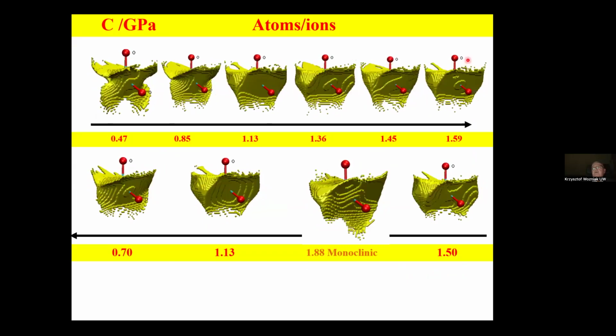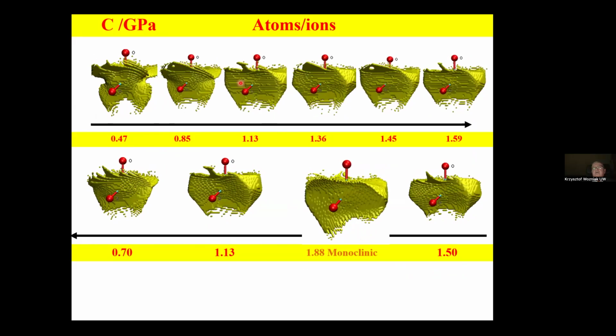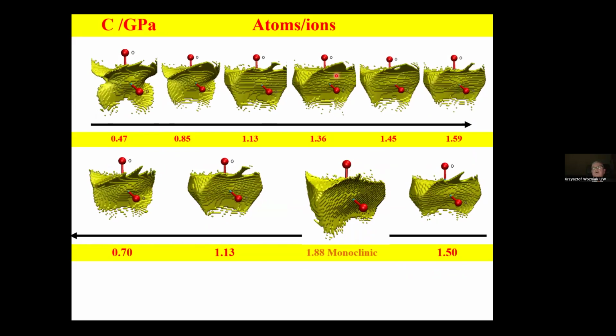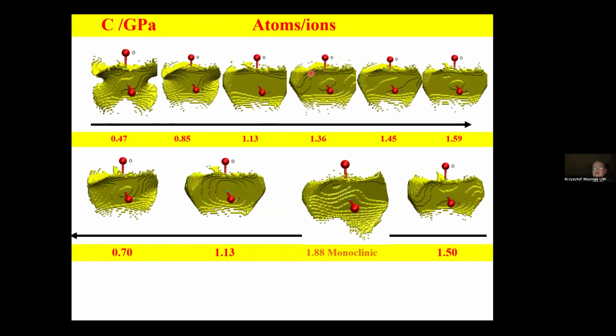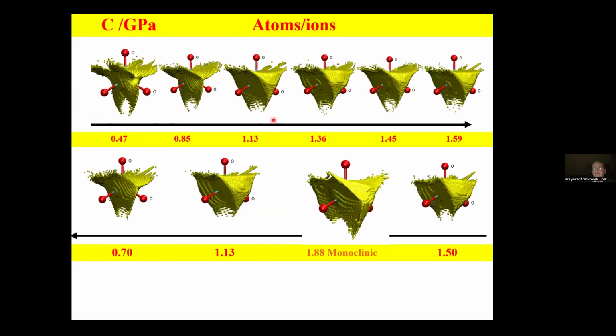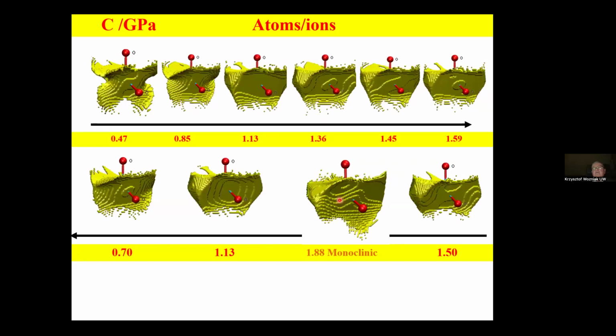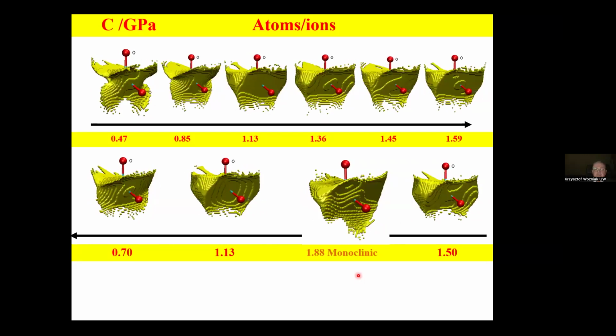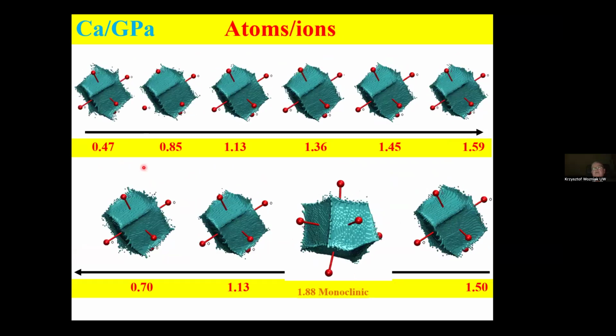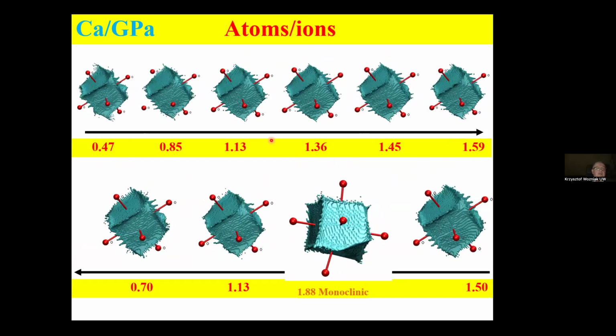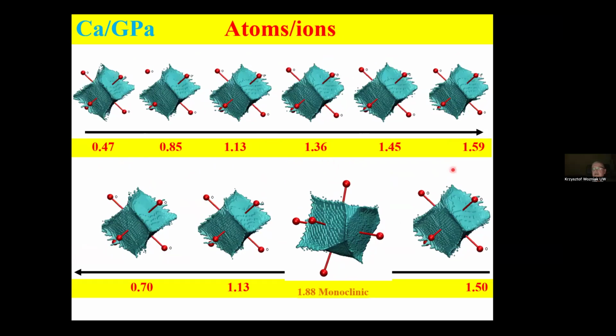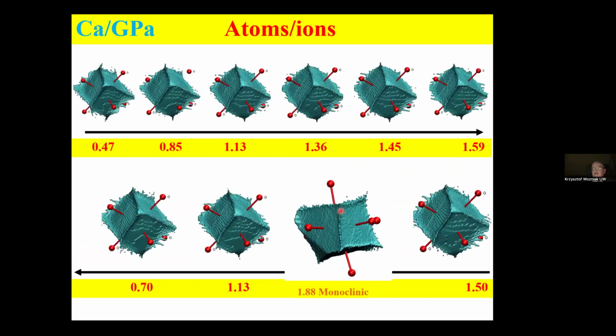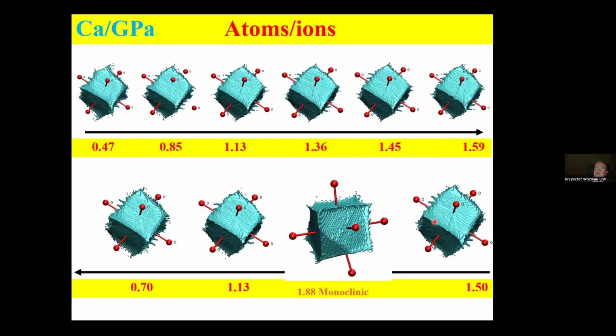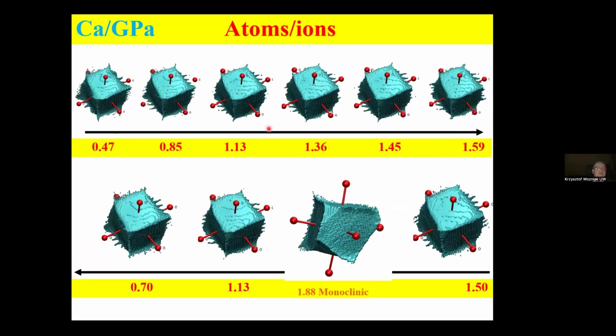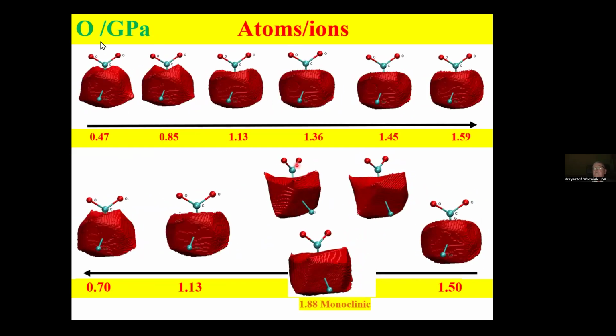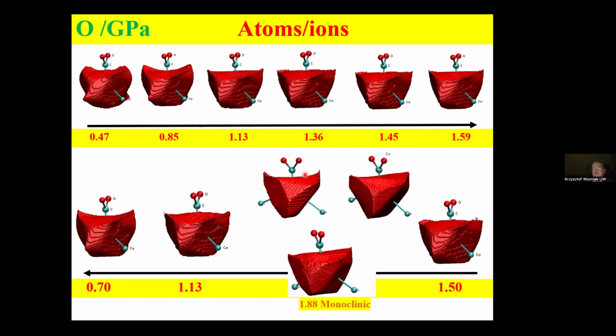Here you see the dependence of atomic basins on pressure, and they change a little bit. We saw how small those changes could be. And there is a bigger change when we go to the monoclinic phase. But we have to find new ways of quantifying these effects, because these changes of shape do tell us something. They tell us about changes of interactions. These are the atomic basins for the calcium ion. And when we go to the monoclinic phase, we see new facets appearing in this atomic basin. So when we have a phase transition, the change is big, but within a given phase, the change is really gradual. The same for oxygen atoms, where after the phase transition we're getting three independent oxygen atoms.